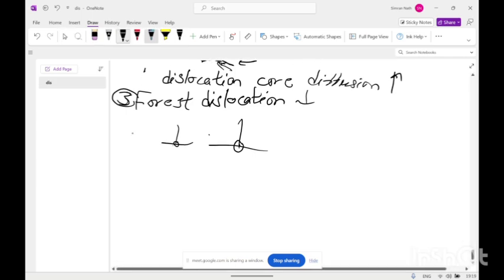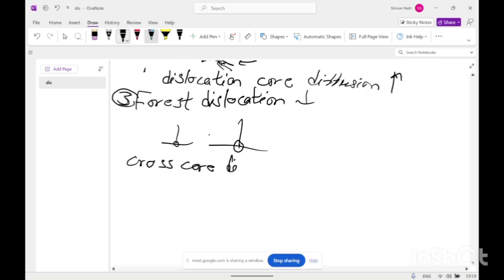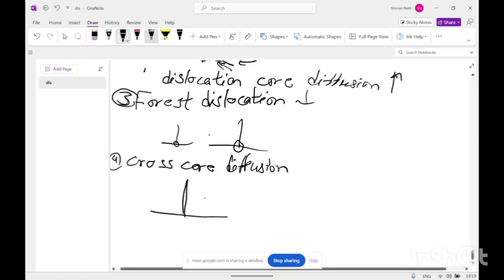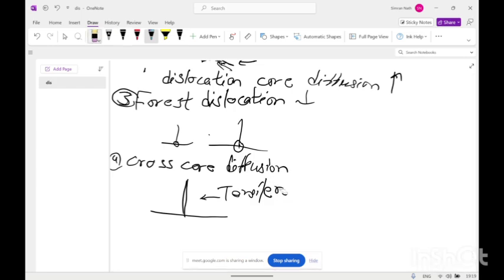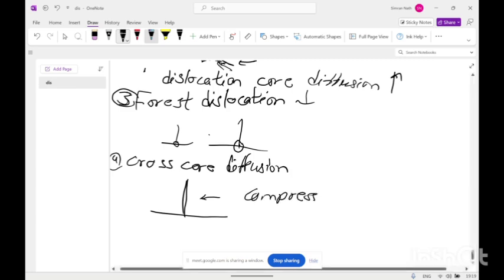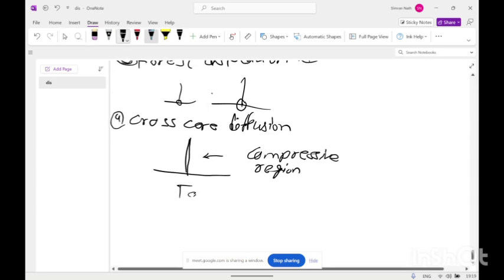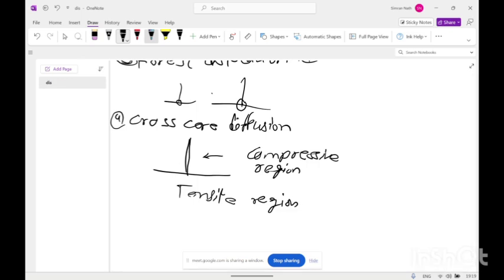Next is the cross core diffusion. Cross core means around the dislocation, above is the compression region, and below the dislocation there is a tensile region. So the diffusion of solute atoms can also happen along the strain field of the dislocation, from compressive to tensile, or tensile to compressive.